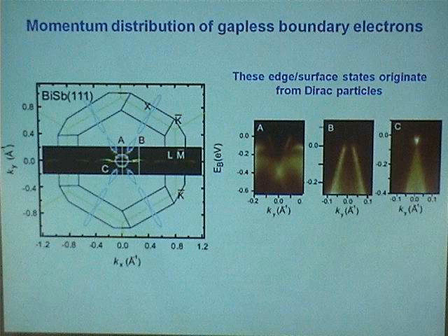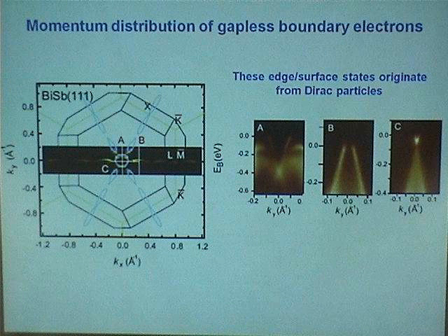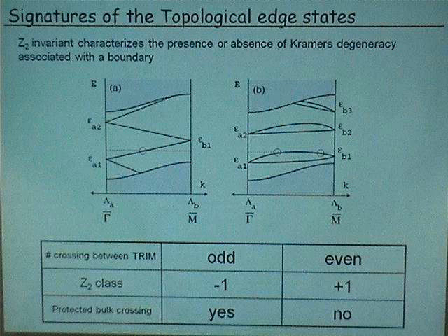Now one can see that the fact that it has bulk linear-like bands, when you impose a boundary condition of some sort, the surface state, whatever you get, it's unusual if you look at this just Fermi surface alone. But the band structure, it looks like it is coming from the bulk band by imposing boundary condition, because it's all linear. And the bulk bands are linear.